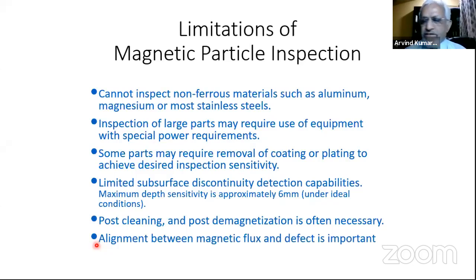With a coated surface, you cannot do MPI. As I said, you will have to demonstrate that the process is working. Otherwise, you have to remove the paint. Sensitivity has to be established. People claim you can do MPI 6 mm below the surface, but unless it is demonstrated, it is difficult to accept. Post-cleaning demagnetization many times may be required, which is an additional step which is required to be followed.